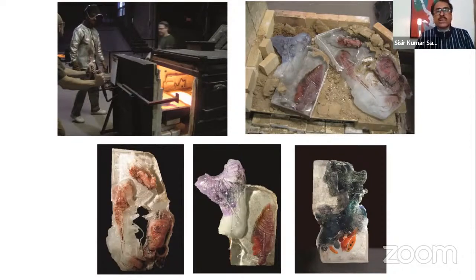Normally, in my type of work, it takes from 10 days to 28 or 30 days for the annealing cycle inside the kiln. As the pieces become thicker and more complex in form, it takes more time for annealing. And one should know the annealing schedule, how to come down from the solidified state, starting from 650 degrees centigrade to 500 degrees centigrade, which is called the stress point or annealing point.